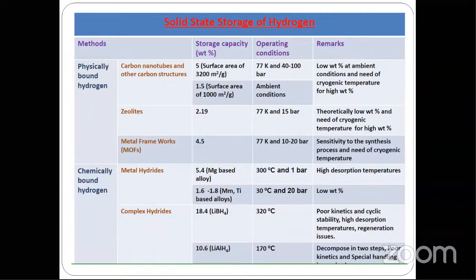Then, if you go for chemically bonded hydrogen, the chemical option, we have metal hydrides and we have complex hydrides. If you see this magnesium-based hydride, it can store 5.4% at 300 degrees centigrade and 1 bar. A little bit temperature is high. It means that we have to give high temperature to release the hydrogen from the magnesium-based alloys. That is one of the drawbacks of magnesium-based alloys.